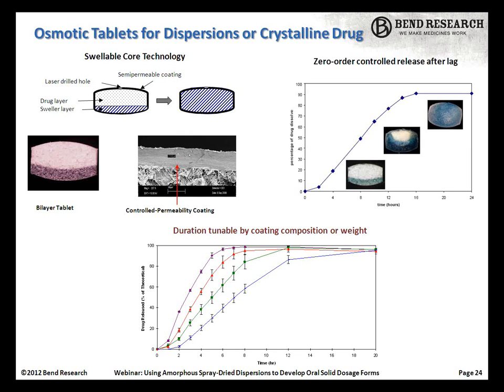and it's extruded out of the laser-drilled orifice. The bottom right here shows the range of dissolution profiles typically obtained. This osmotic system will give zero order profiles like this, and we can control the release rate over a pretty wide range.